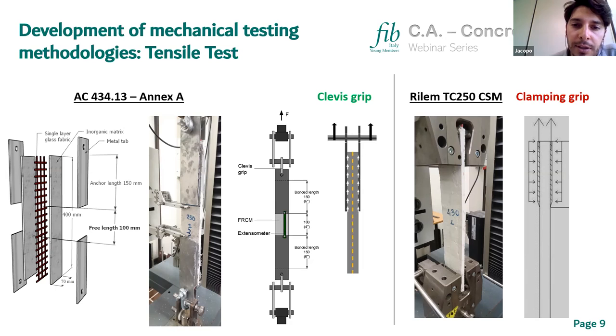So in this case, the load is transferred to the fabric only through shear stresses at the interface between these metal tabs and the inorganic mortar. So we do not apply compression forces at the ends of the specimen. So in this case, we represent the real conditions on site because the fabric within the matrix is free to slip. And so we can also evaluate what is very important, and that is the bond between the fabric and the mortar. While the RILEM Technical Committee 250